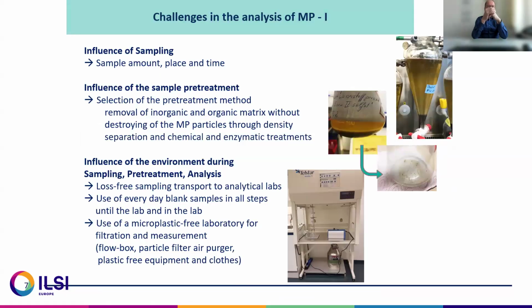What are the challenges for the analysis of microplastics? Very shortly, we have an influence of the sampling: which sample amount we have, the place and the time. We have a great influence of the sample pretreatment, that means which pretreatment methods we use for the removal of inorganic and organic matrix without destroying the microplastic particles. Then we have an influence of the environment during sampling, pretreatment, and analysis. That means we should have a loss-free sampling transport. We have to use everyday blank samples in all steps until the lab and also in the lab.